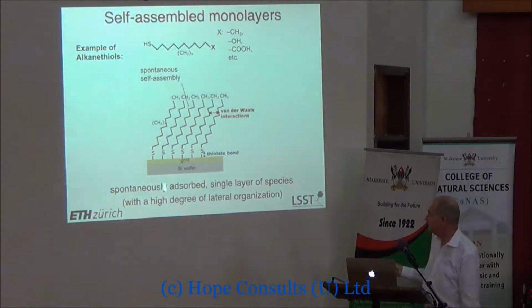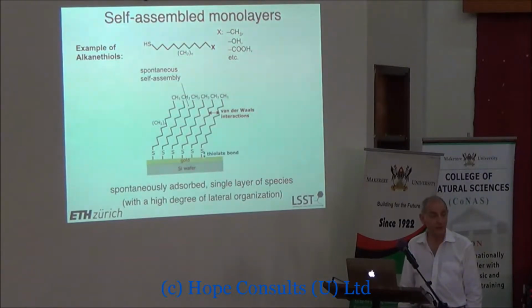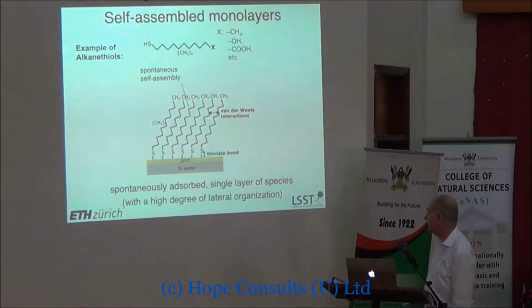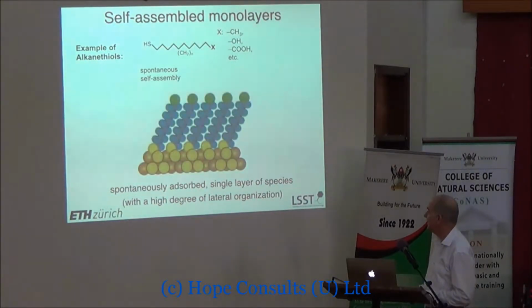So we have a surface that's just close packed with these chains, all oriented together and presenting this functionality to the outside world. So if we just take this gold surface and dip it into this solution, we produce a concentrated layer of functionality of whatever was stuck to the end of the thiol molecule. And it's a very easy process to do, and we do it every day in our lab. So they look something like this in the end. Here's your functionality, here's your gold, and here are the chains of hydrocarbons that are causing the organization.